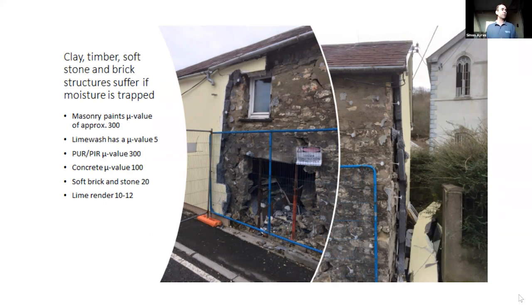Lime wash is out of place in my scale, but is 5, so it's very low. Masonry paint, 300. So when you get up into much more than 20 or 30, something like that, you can end up with problems. And particularly you would have problems when you are reusing or renovating a building, because they're built differently, and if you're using materials with much higher mu values, you're going to trap moisture. Same goes for newer buildings built out of some of the natural materials. Next slide, please.